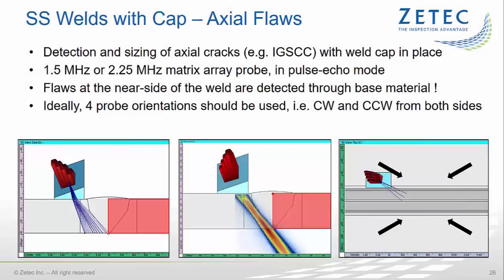If the weld cannot be removed prior to the UT examination, no probe can be positioned on the weld. Therefore, the detection of axial flaws, and specifically IGSCC near to the ID surface, can be quite challenging. In such cases, single matrix array probes in pulse echo mode can be used to skew the sound beam under the weld cap. Since the sound beam essentially propagates in base material, shear waves can reliably detect flaws at the near side of the weld.